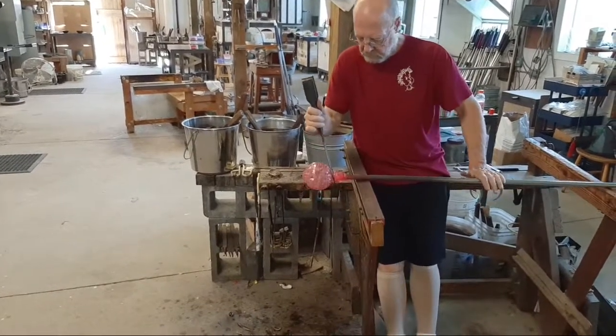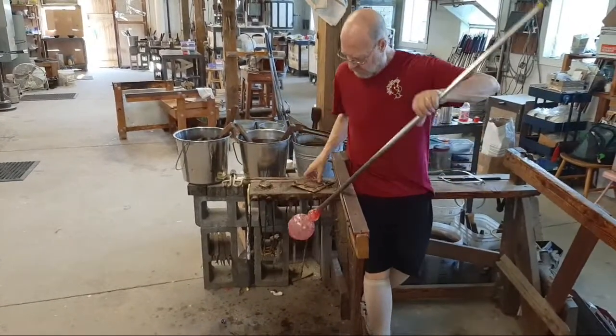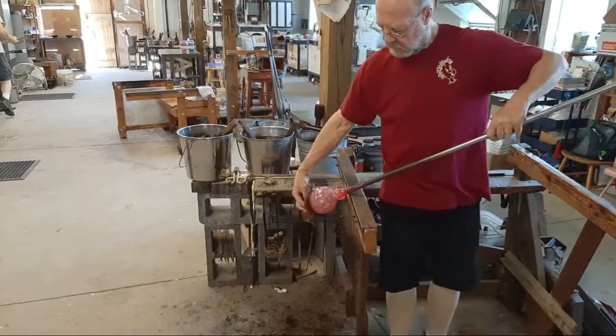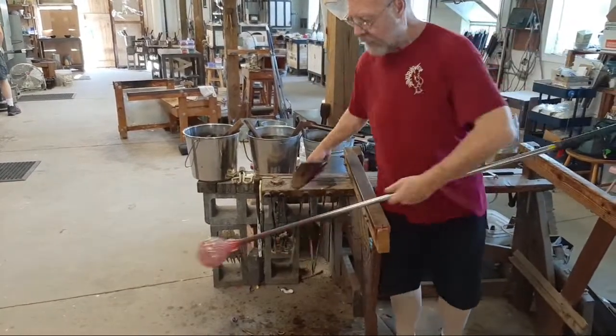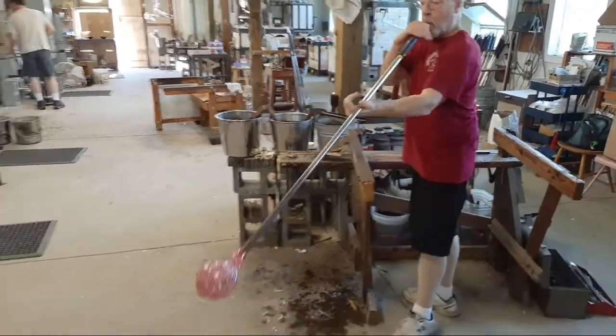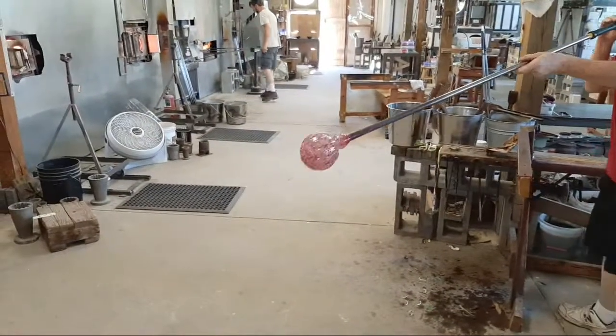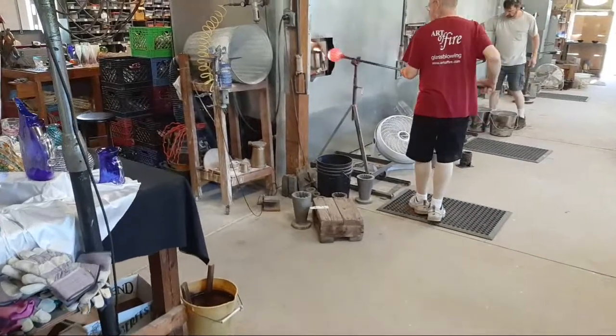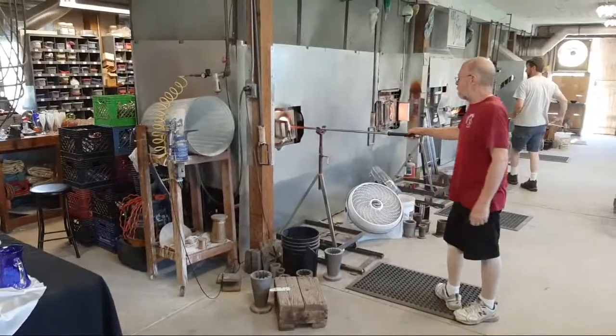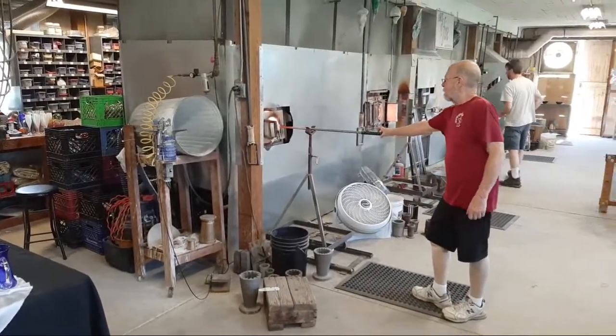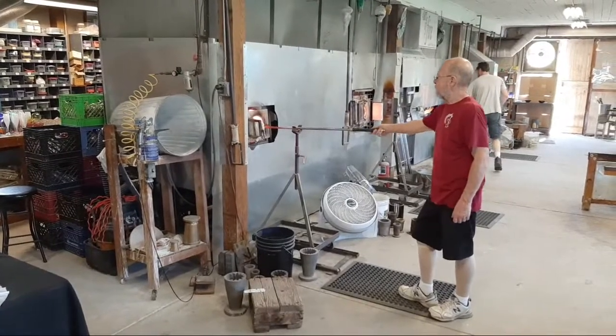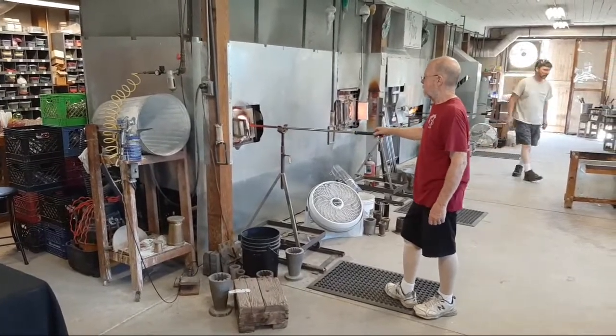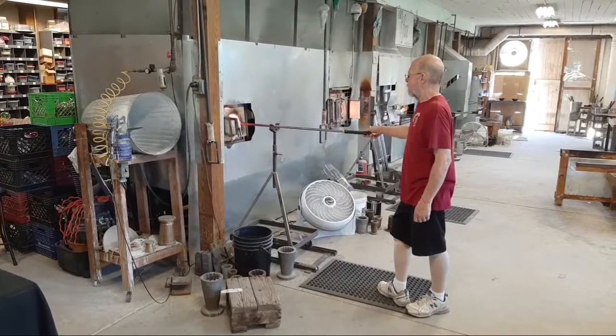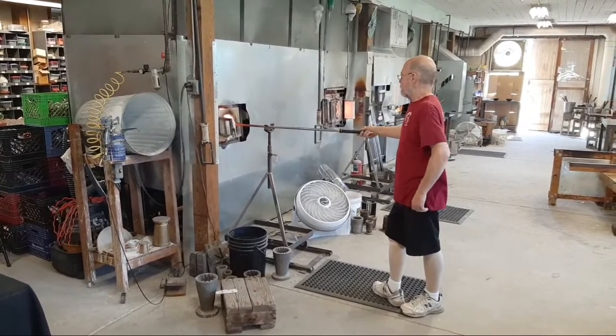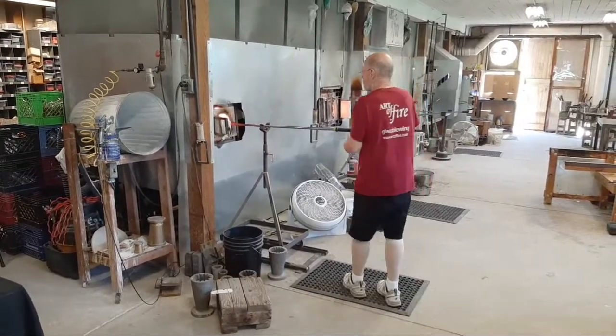He reinforces the jack line again. He's cooling it with newspaper that time rather than the metal tabletop. And he'll blow again, but once more, he doesn't get too much inflation at the very end. If he let the bottom of the vessel get very, very thin, it's quite likely that it could crack later in the process and we'd have difficulty making the piece. So we like to keep a reservoir of thick glass down toward the bottom of the vessel.